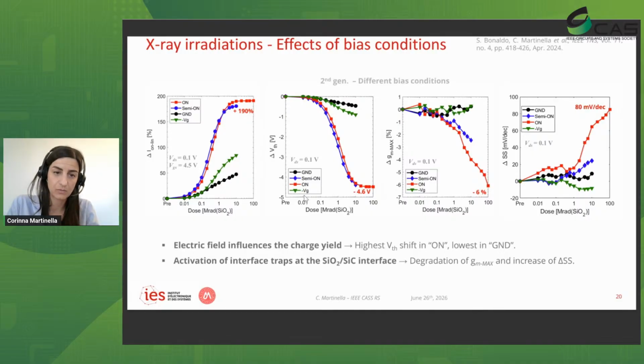If we take a look, for example, at the delta of the threshold voltage, we have here the dose, so we can see all the steps of dose, and here the value of the threshold voltage. We can see that the worst condition was when the device was in on bias or semi-on. In this case, the device was either at 20 volts or 5 volts, and there is not too much difference among them. Then we have the off-state case and then the ground condition.